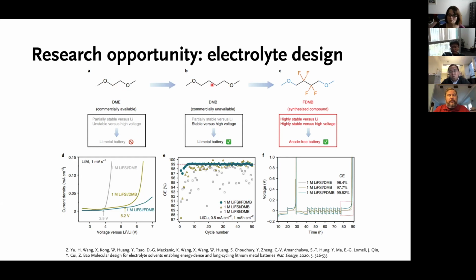And then to further increase the stability, particularly for high potential cathode materials, for instance, manganese-based materials, to substitute hydrogen with fluorine, to fluorinate this carbon, is very helpful. But the catch is that you don't want to fluorinate the carbon right next to oxygen. You have to really fluorinate it away from it, otherwise solubility becomes an issue. So there has been a lot of good success demonstrated. And this is an area that I think a lot of people with a synthetic background, a synthetic interest, can contribute. I do want to mention, however, that cost, a techno-economic analysis, is very important.